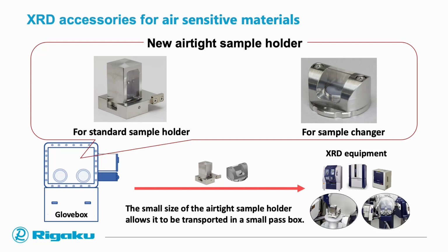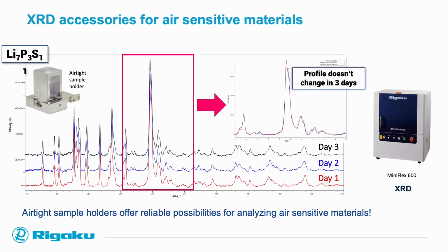On the other side, when we have air-sensitive materials, which we have to store or prepare in the glove box, of course, Rigaku also offers airtight sample holders, which are stored and filled in the glove box and then transferred, due to their small size, in small pass boxes to the XRD equipment, where they are then measured. As such, in this case, a lithium phosphorus sulfur compound, which we left in the airtight sample holder over 3 days, and as you can see, the profile doesn't change. So over a long time range, the material stays stable inside these airtight sample holders, which offers a great opportunity to analyze and investigate air-sensitive materials, which can also be done, for example, in the Miniflex 600, but also in bigger systems like the SmartLab systems.